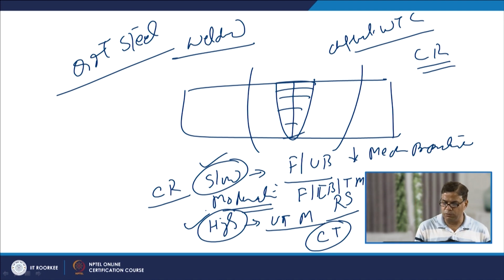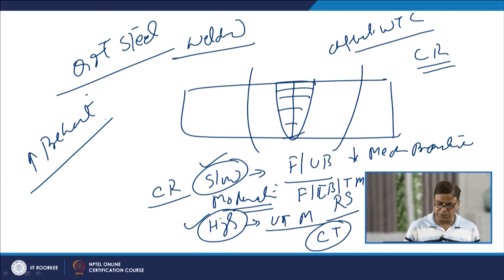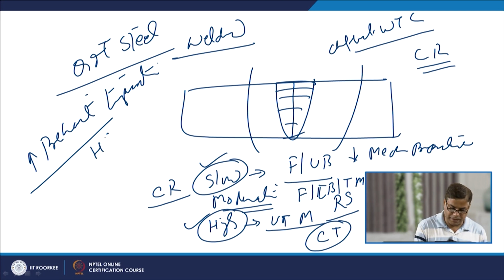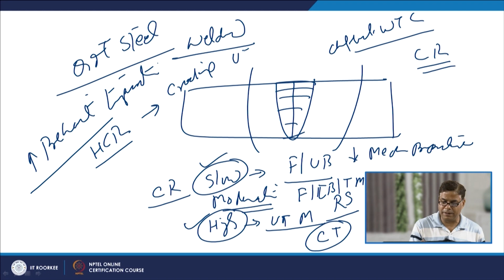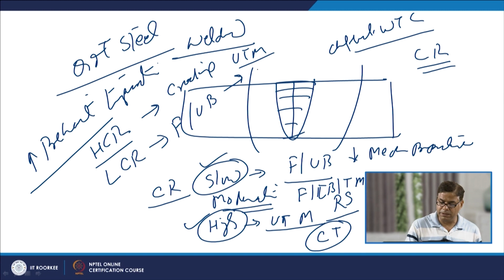So, what can we do for this purpose? We have to avoid excessive high preheat. Preheating is needed, so an optimum preheat is to be used. If the preheating temperature and interpass temperature during welding of the Q&T steels are low, then a low preheat temperature will lead to a high cooling rate, and that may increase the tendency for cracking due to the formation of untempered martensite. On the other hand, if the preheating temperature is very high, it will lead to a very low cooling rate, and a low cooling rate again will lead to the formation of ferrite and upper bainite, and these will deteriorate the mechanical properties in terms of reduced notch toughness and yield strength.